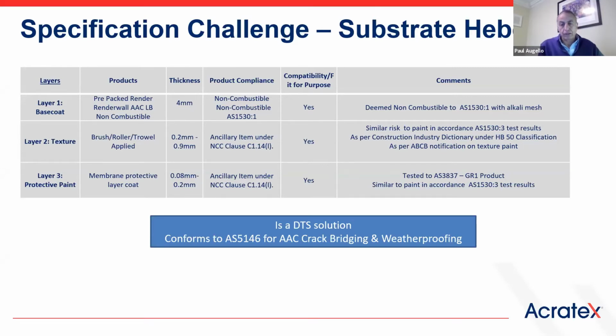More importantly, what we've also done is test both paint materials and textured paint materials to 1530 part 3, which is generally the rule of thumb for building products, to determine their ignitability and smoke, and they all fall within the same test results when you look at the test data. And then obviously the last one is that paint membrane, which is that important part of the layer, which is actually a Group 1 product. So that adds that little level of more comfort to the whole thing. That complies with Group 1.